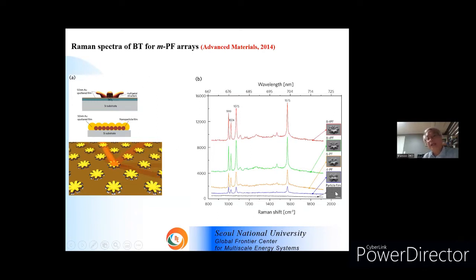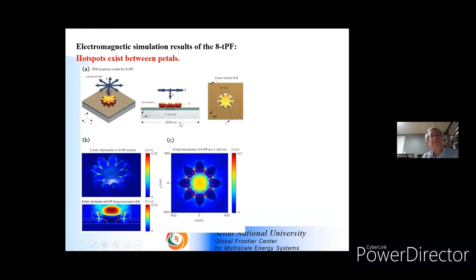As we increase the petal number, you see the Raman signal is significantly enhanced. Electromagnetic simulation revealed that the hotspot exists between these petals. That's the reason why we have a higher Raman signal for a higher number of petals in the flower structure.